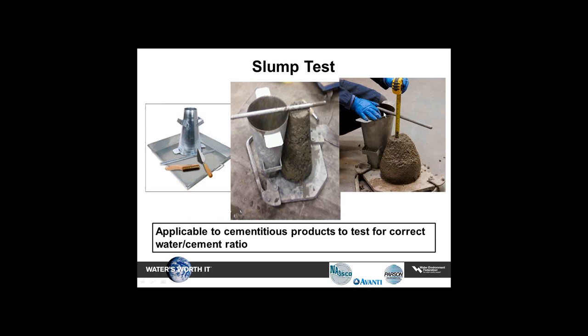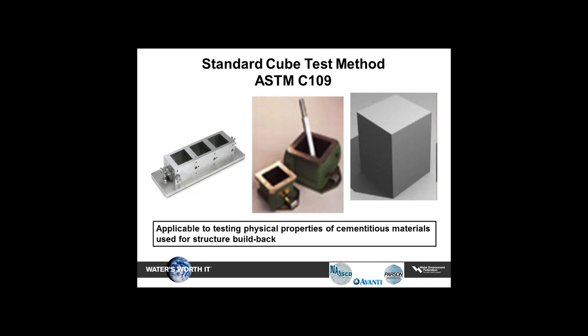Your slump tests, pretty common in the industry, very important for cementitious products to make sure that the water-cement ratio is correct, and that can be something that is specified by the manufacturer and then inspected by an inspector by doing a slump test out in the field.